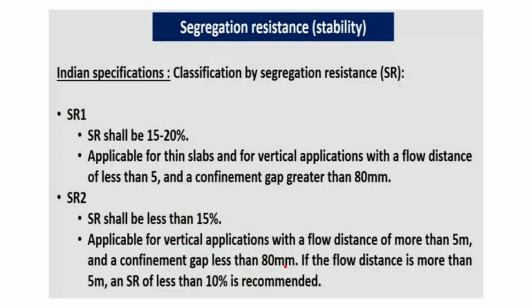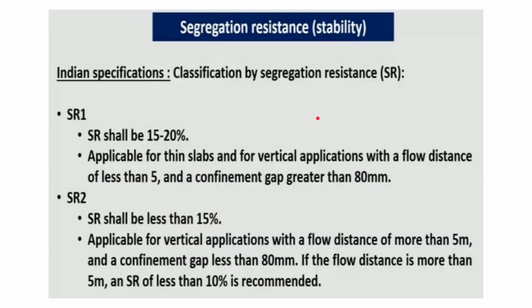But if the confinement gap is less than 80 mm and the flow is also more than 5 meter, then we need to have a very good segregation resistance, that is it should be lesser than 15% or preferably even lesser than 10%. Okay, so that is all about segregation.